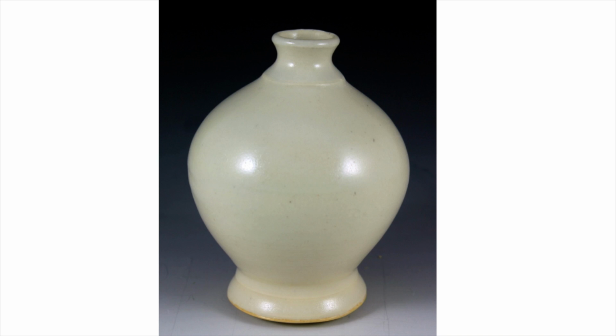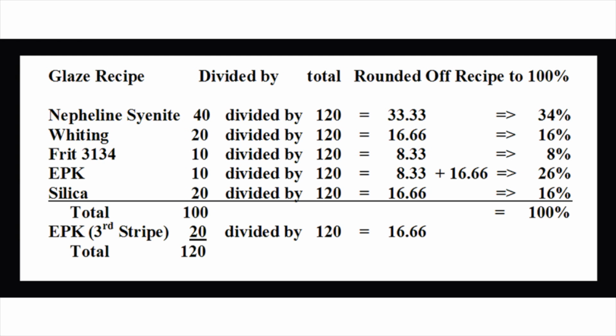This bottle is glazed with that recipe from that third test stripe. Now you need to convert that glaze recipe to 100%. So you add the 20% addition to the total of all the base glaze ingredients, which in this case totals to 120. Divide each amount in the base glaze and the influencing test ingredient by that total, 120.